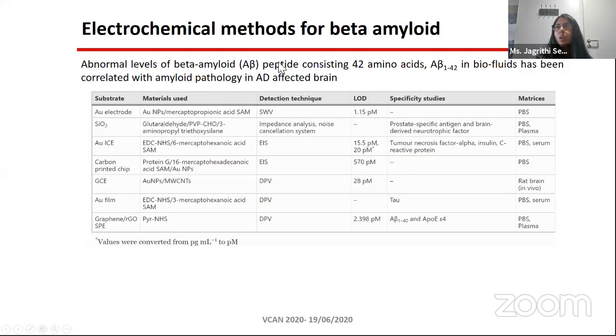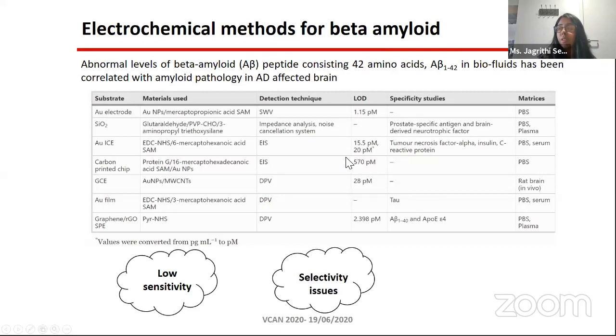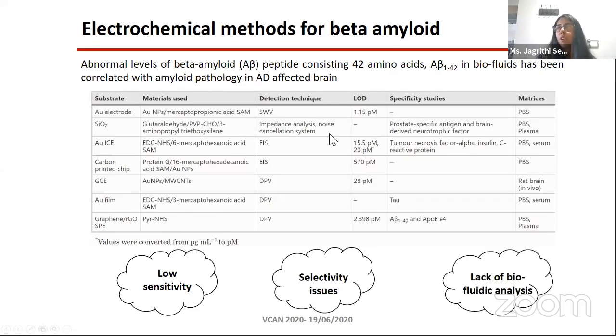So we only focused on amyloid beta with 42 amino acids, which is A beta 42. We detected it from biofluids, especially human plasma and mice plasma, because abnormal levels in the biofluids have been correlated with the amyloid pathology that occurs in the brain of AD patients. The main issues with the existing technology are low sensitivity and selectivity. Either the sensitivity is not enough, or the sensors with higher sensitivity have no specificity against interfering species, which is really important in biofluidic analysis. And there is a lack of biofluidic analysis, because most have not validated their sensors in any biofluids.